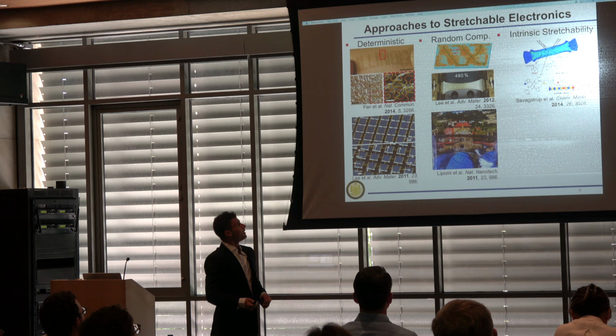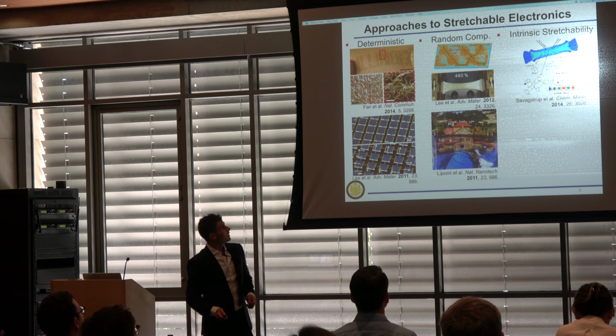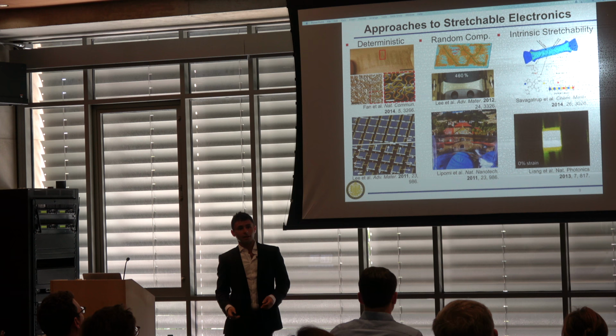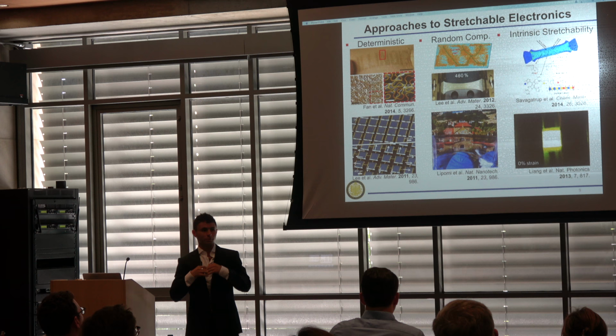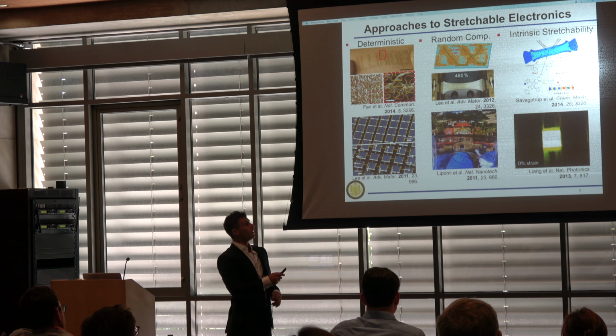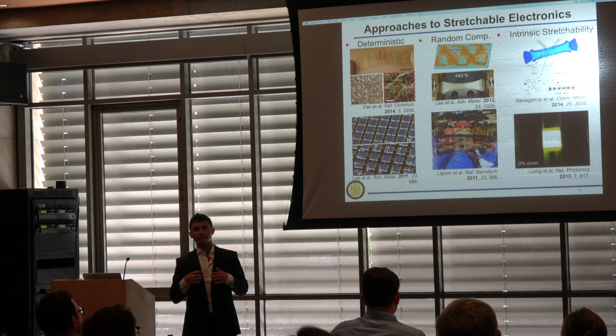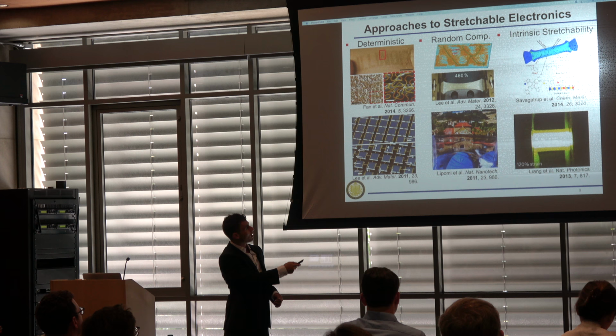The last way is through molecularly stretchable materials, or intrinsically stretchable devices. In this method, the strain is actually being accommodated by the molecular structure of the functional material itself. So you actually have stretchable electronic materials, and this is beneficial for devices that use conductive and semiconductive materials, since you can maintain a contiguous film as you stretch the device. Here we can see a solar cell up top, and then an LED that has been stretched to 100% strain.